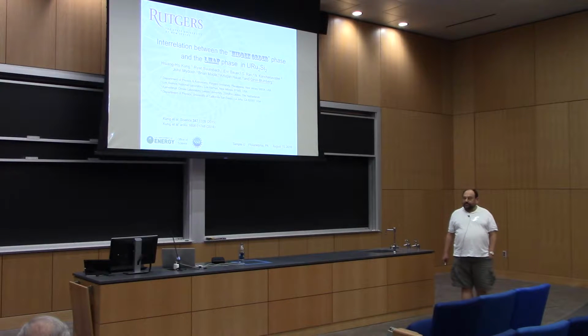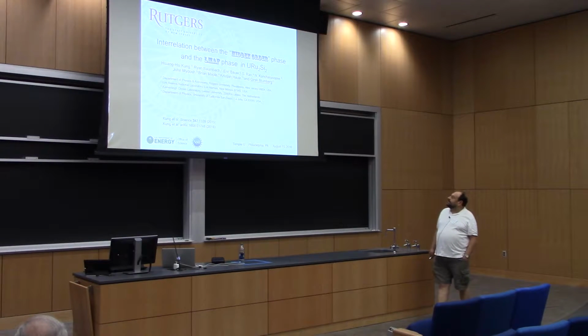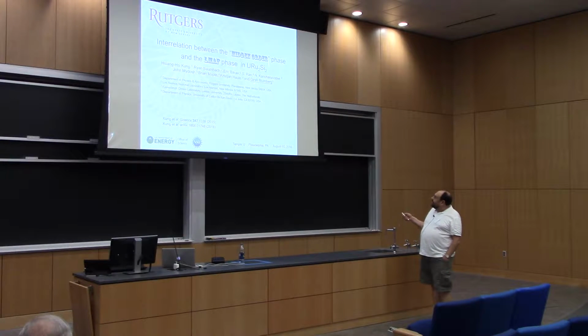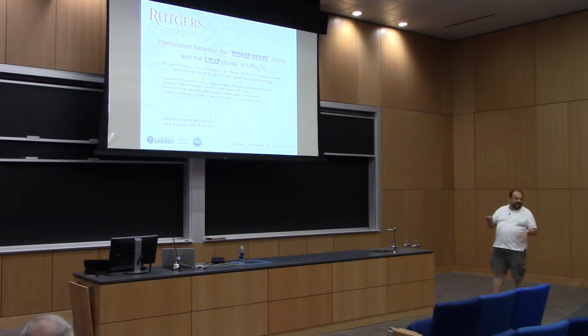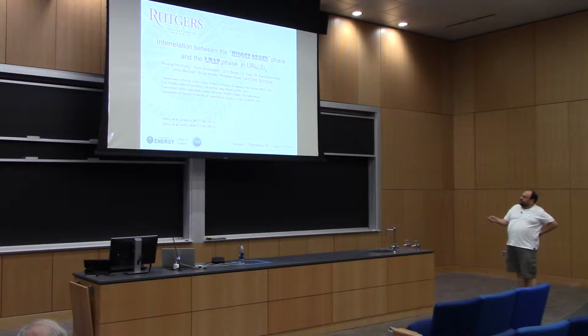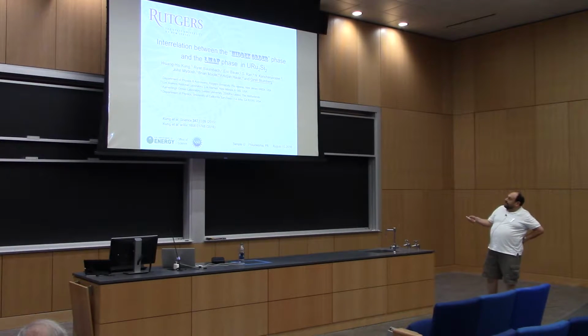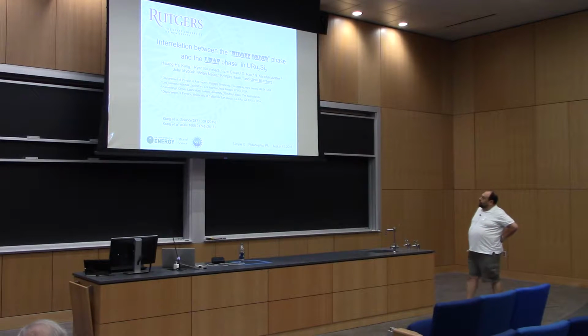Since then, we collaborated with Brian's group, and we got these beautiful iron doped samples, which Brian discussed in the first talk, and we were able to apply a similar analysis when the system was moved from the hidden order into the large moment antiferromagnetic state. So I will mainly talk about this connection between these two states. The work was done in collaboration with people at Los Alamos, Ryan Baumbach, who is now in Florida, and Eric Bauer, and people in Brian Maple's group. Sean was the leading author on these two papers. The most recent paper is presented on arXiv.